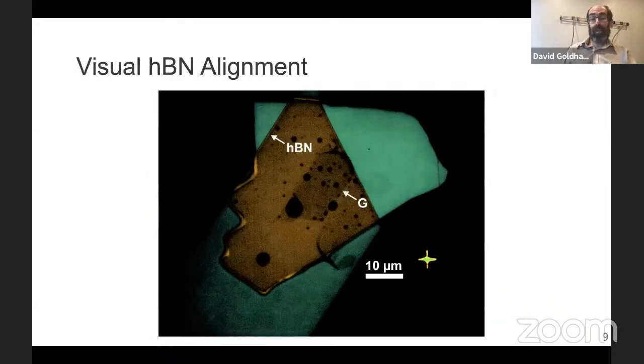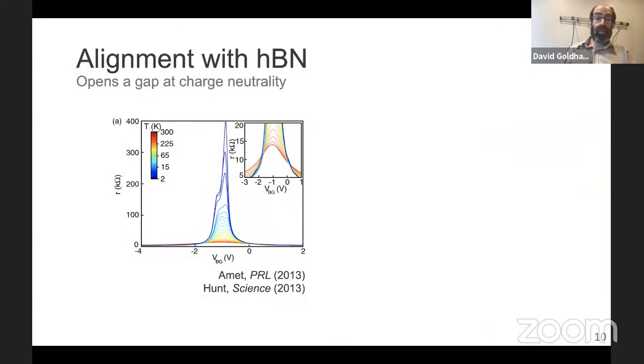And in fact, when we looked back at our photos taken during construction of the sample, you can see that the graphene and the boron nitride have facets that are almost aligned. So one could see by looking at this that it's aligned to within about 1 degree, unless it's actually off by 30 degrees, and we can't tell which facets they are, but it turns out it's aligned to within 1 degree. All right, so it was already known for a while that alignment with boron nitride can change the behavior of graphene, even though I said that boron nitride is typically thought of as a pretty inert dielectric.